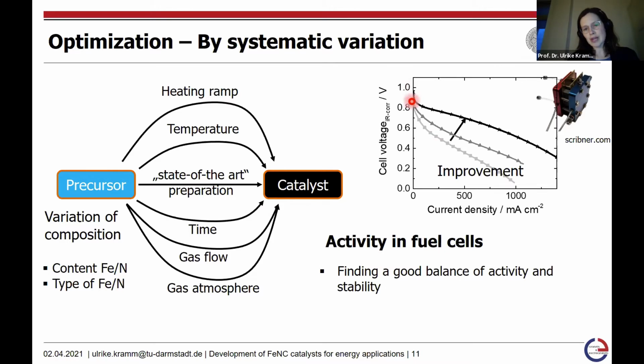This is a polarization curve where you have the cell voltage plotted as a function of the current density. As you would like to maximize the current density at 0.8 volts, you prefer to go in this direction for the optimization of the catalyst material. The bottleneck for this type of preparation is that you need to find a good balance between the activity and the stability of the catalyst material. This is a little bit more complex. I will probably not go too much into detail in relation to this.